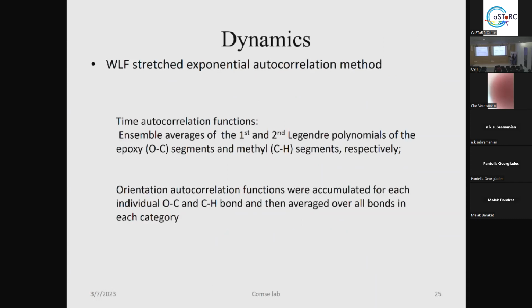After that, we did it in a second way, which is the WLF method, taking into account the first and second Legendre polynomials of the epoxy segments OC and CH, in order to see how these two bond vectors behave, and so to have a bigger picture of the dynamics of the system.